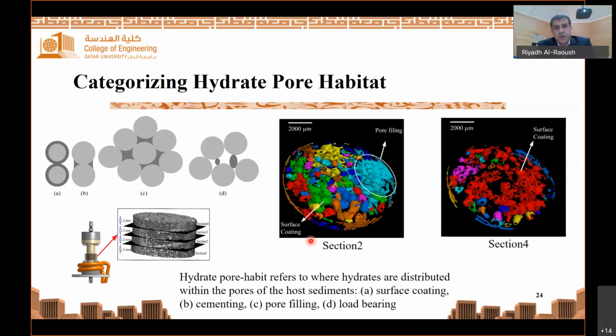These segmented images show the outcome of the hydrate formation experiments. You can see from these tomography images, three-dimensional images, we can identify 3 types of hydrate formation, namely surface coating here, cementing here, and pore filling here. Such observation in a non-destructive fashion is very important, not only to predict gas production from methane hydrate sediments, but also to evaluate the safety and the structural stability of hydrate reservoirs.